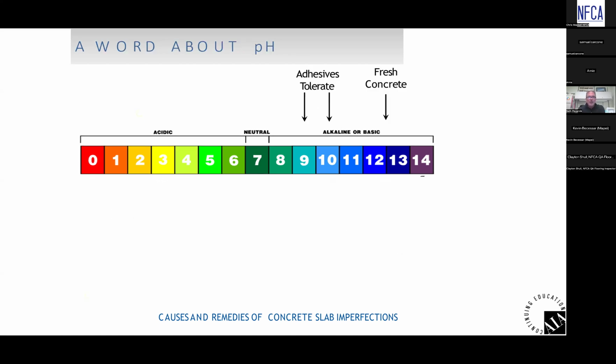Typical adhesives tolerate 9 to 10 on the pH scale. Present day, you'll see ones that go up to 11, even 12 on the pH scale. Fresh concrete is around 12 to 13. But what happens, as I said earlier, is concrete carbonates when the carbon dioxide in the air reacts with the concrete. It'll carbonate and it'll drop the pH down a little bit lower than where it is when it's fresh. So it's suitable for adhesives in flooring.